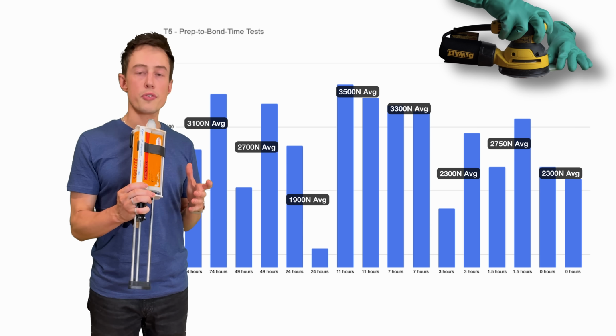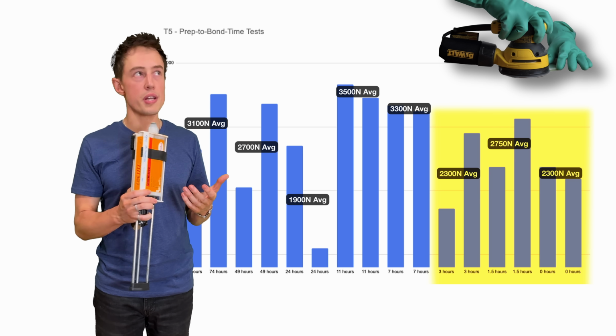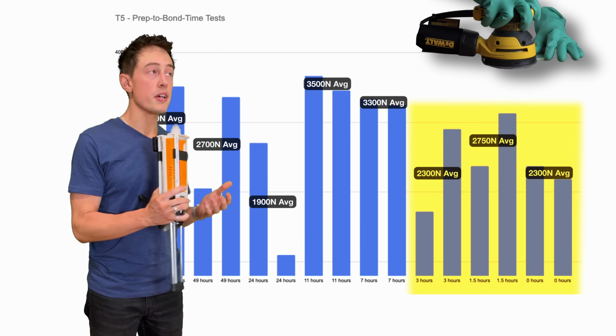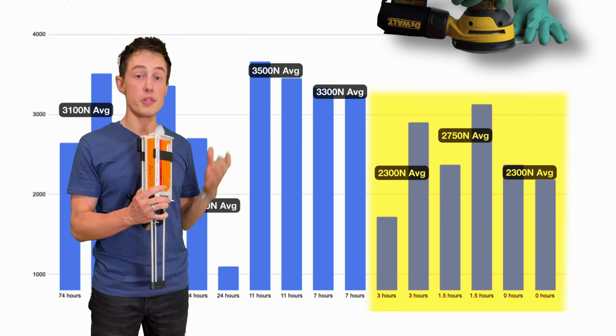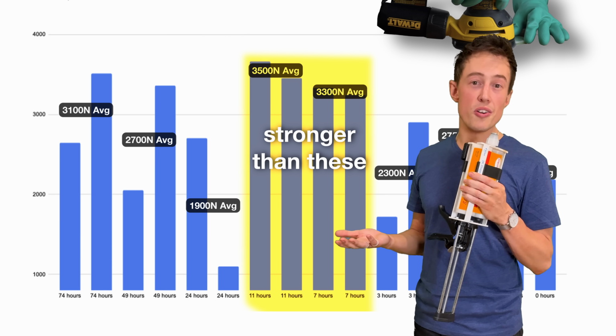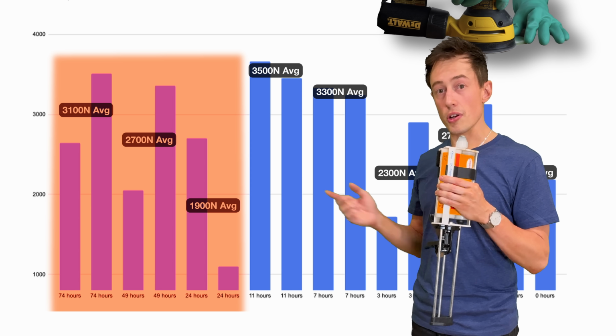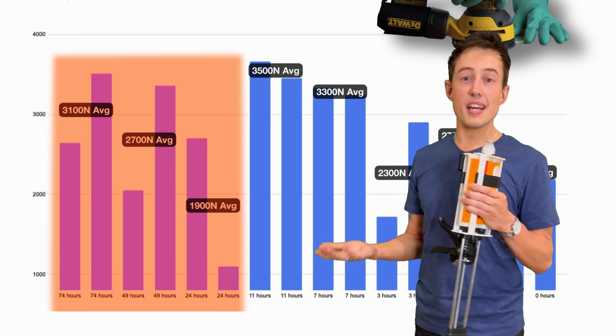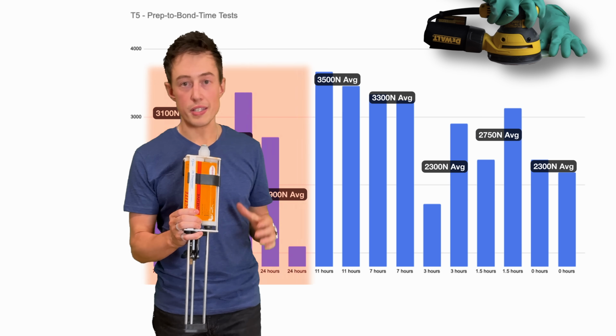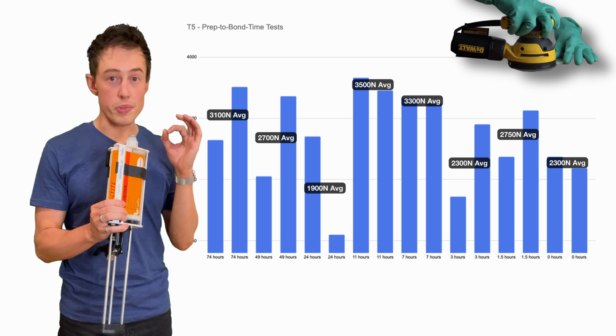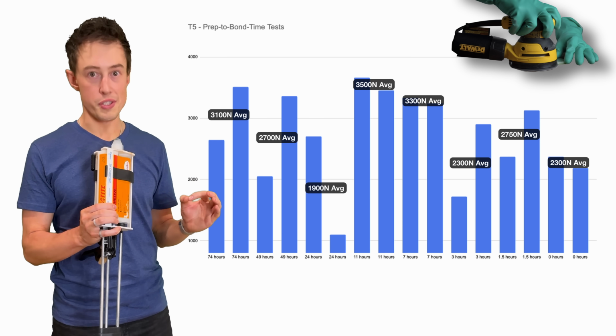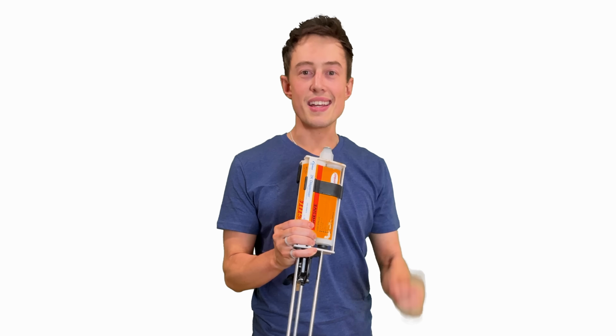If I squint and look for trends, it does seem like the orbital sander is less consistent, especially because we'd expect the more recent results to be stronger than these. And it's kind of hard to ignore that a lot of the data after 12 hours is all over the place. This data is incomplete and it's imperfect. It still has value, but we should be really careful not to draw strong conclusions from it. What we should do instead is collect more.